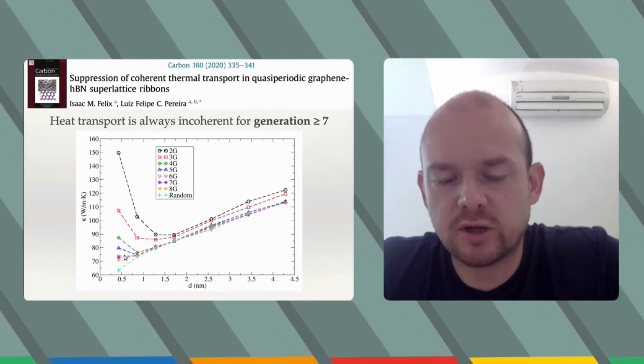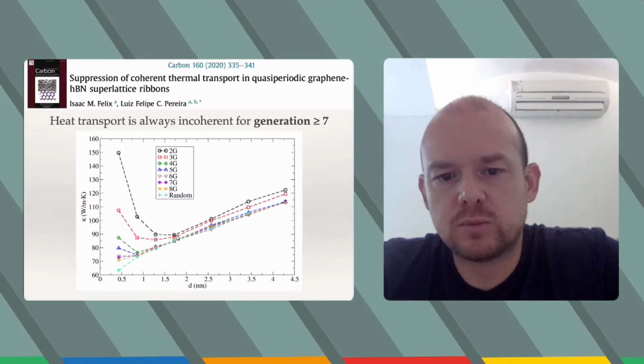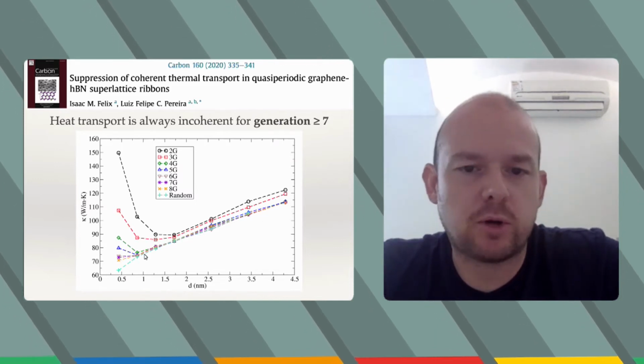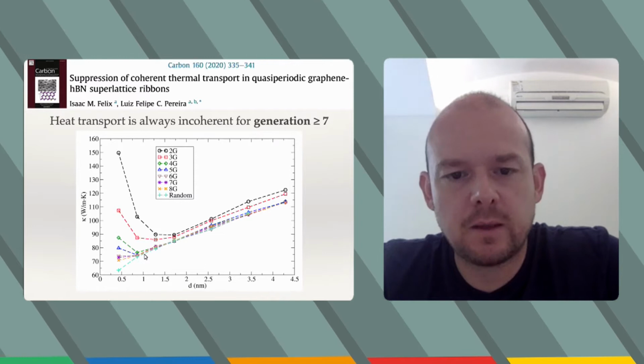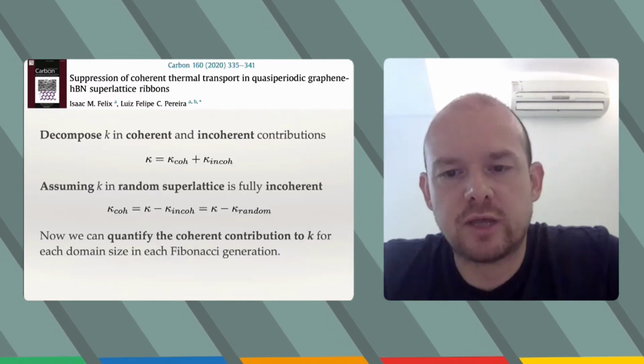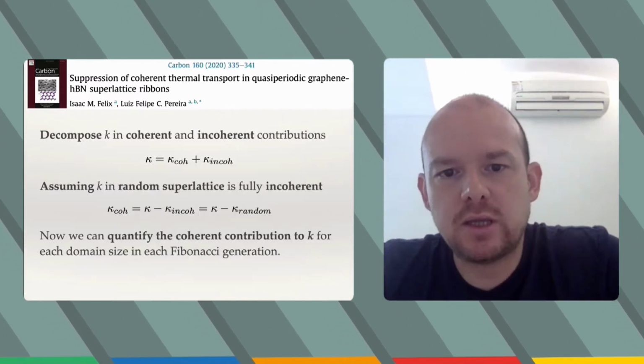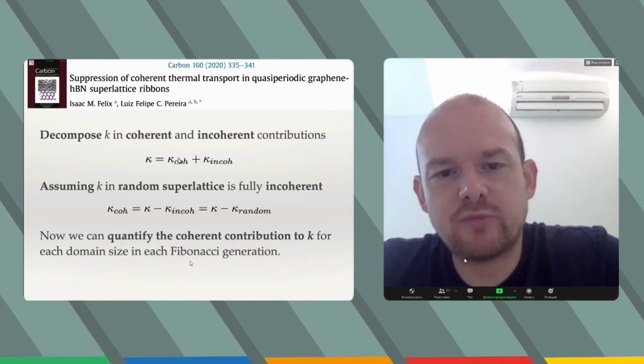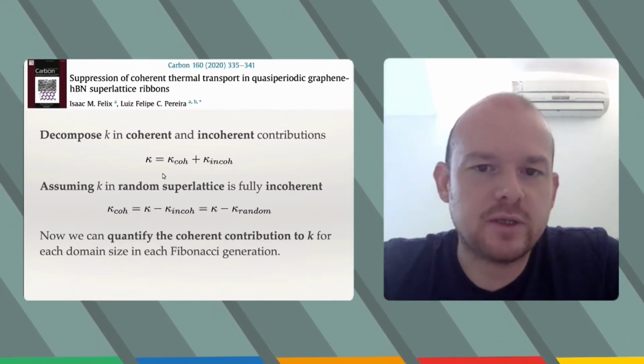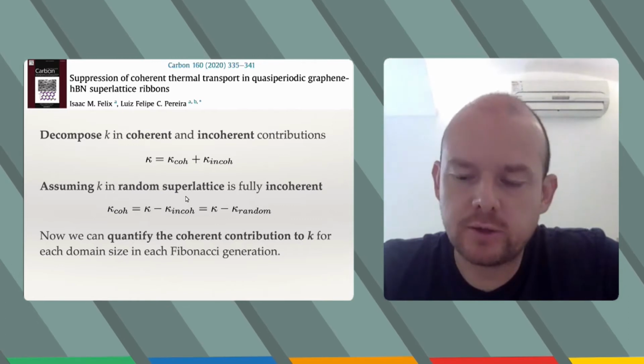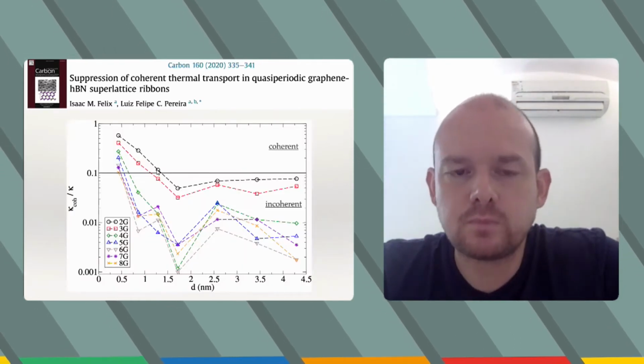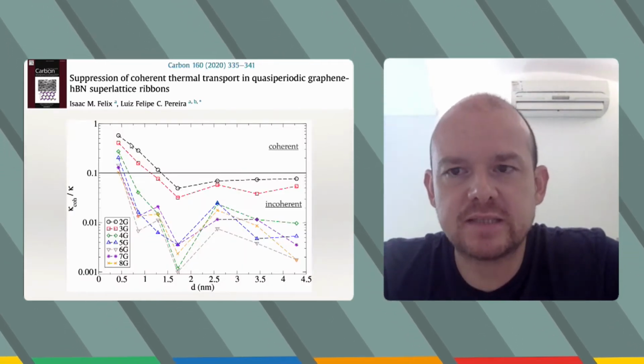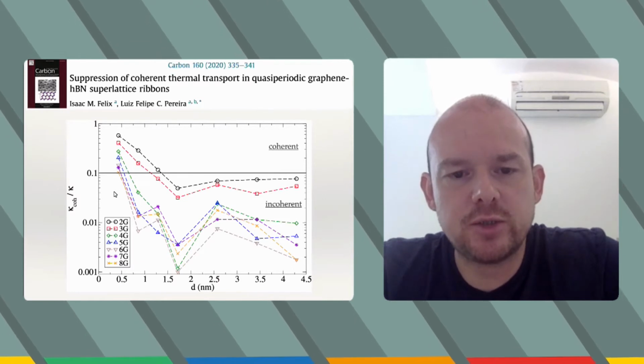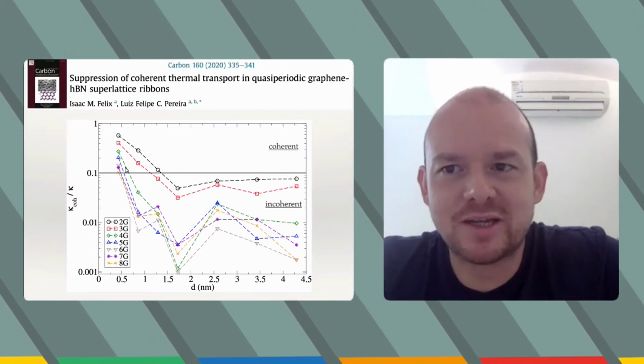The blue line here shows what the thermal conductivity would be for a random superlattice where graphene and boron nitride domains are randomly placed for a given domain. I can actually quantify how much of my thermal conductivity is coherent and how much is incoherent by comparing to the random superlattice. And what we see is that as we increase the generation in the quasi-periodic sequence, I'm almost done.